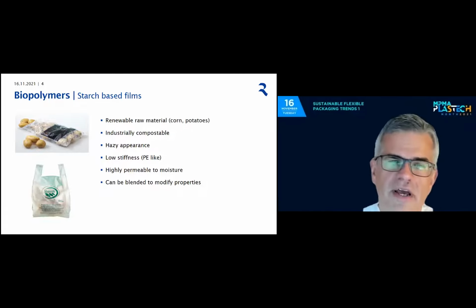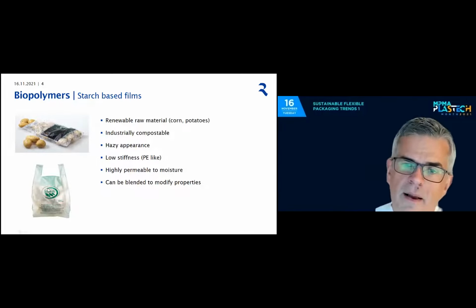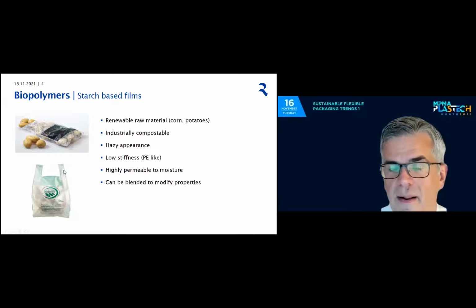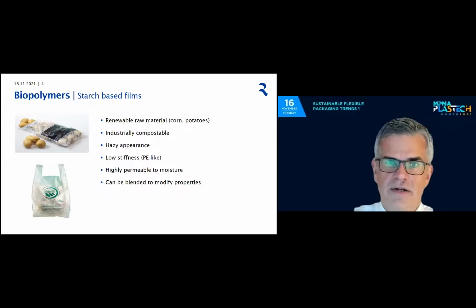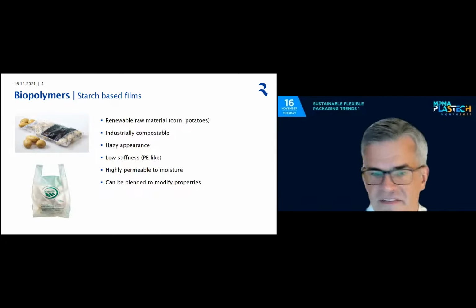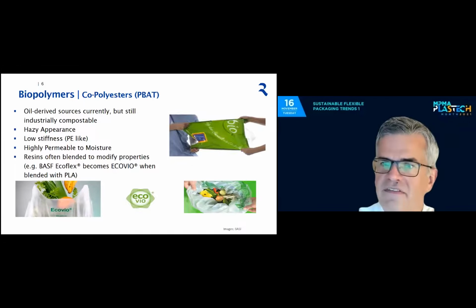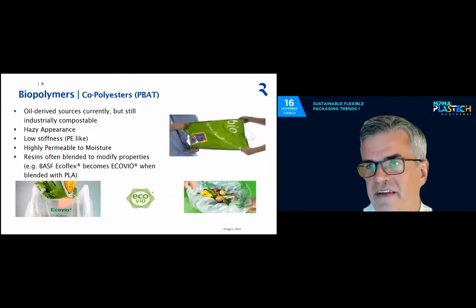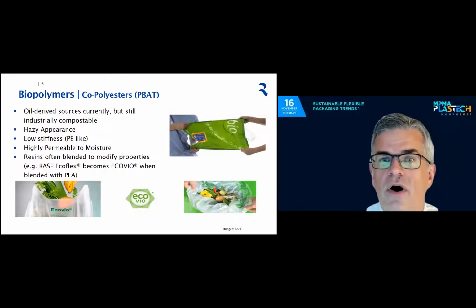And I will show you later, in the next slide, what one can do by machine technology, because these bags have one disadvantage, and this is the elongation if I put some goods in these bags. And the same is true for biopolymers based on copolyesters, which are usually oil-based solutions, but they are still compostable. They show more or less the same disadvantages in terms of properties: hazy appearance, low stiffness, high permeability to moisture, like the starch-based polymers.